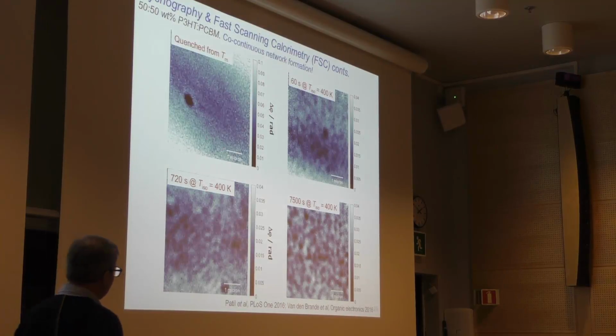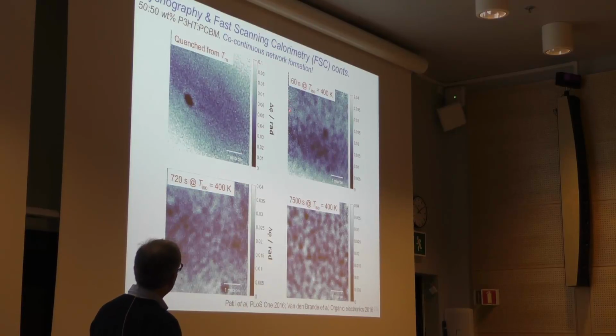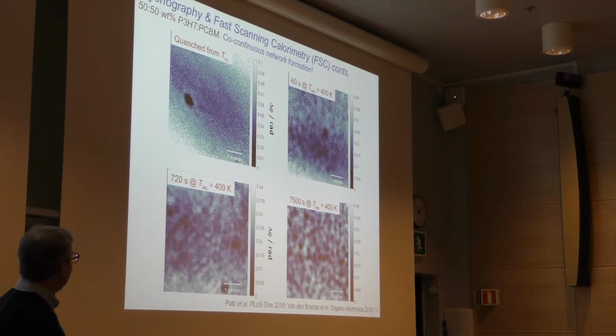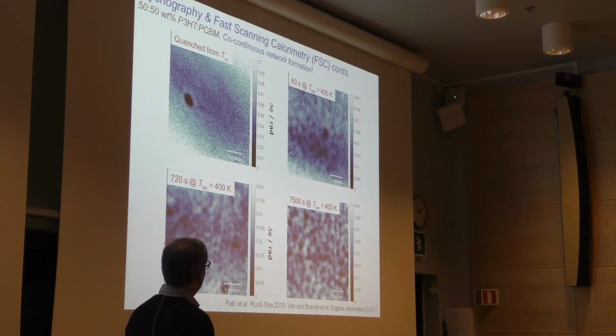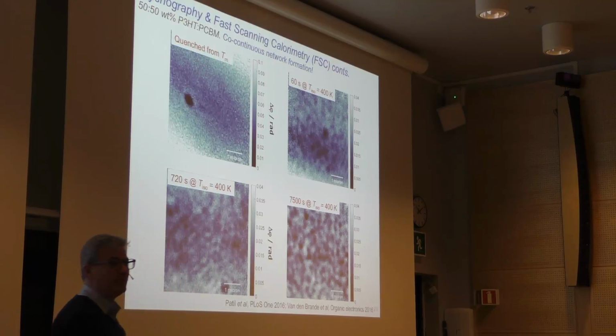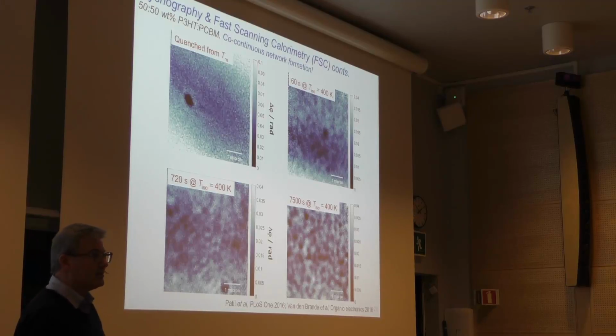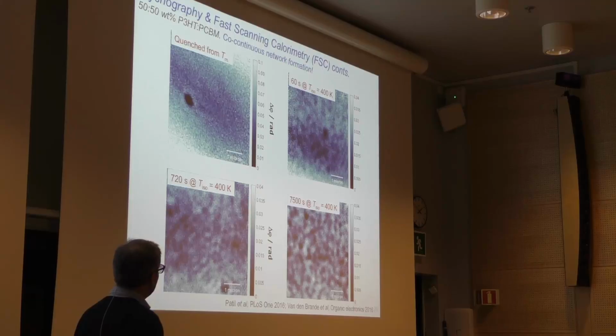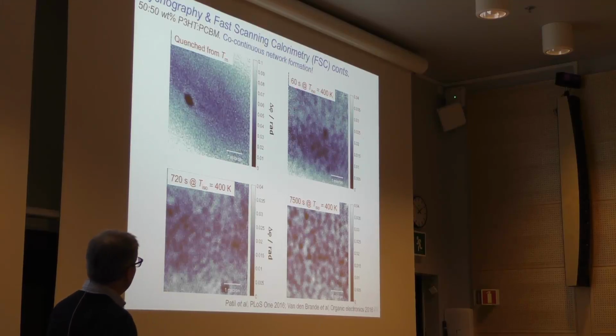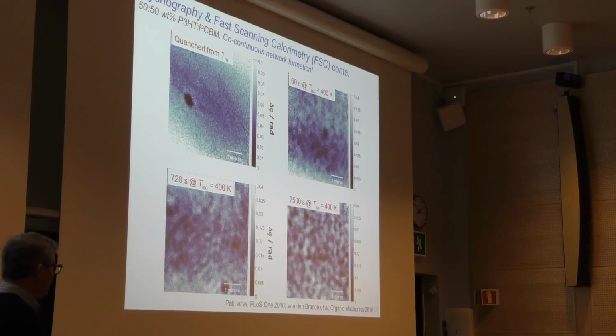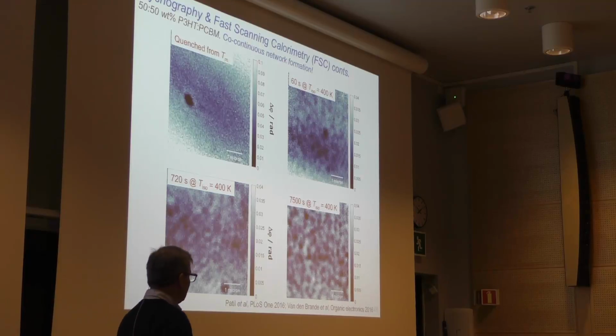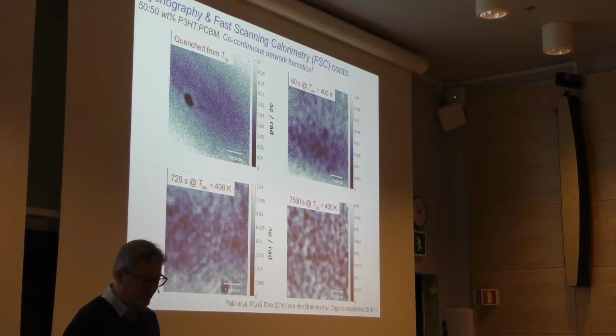And by doing this, we can see then that the co-continuous network in P3HT:PCBM, which was the standard sample that we looked at here, how these co-continuous networks form. In the first case it was just quenched from the melt, which can be done very quickly with this setup that I just described to you. And one can then, after various annealing times, look directly into how the morphology has developed as a function of annealing time.